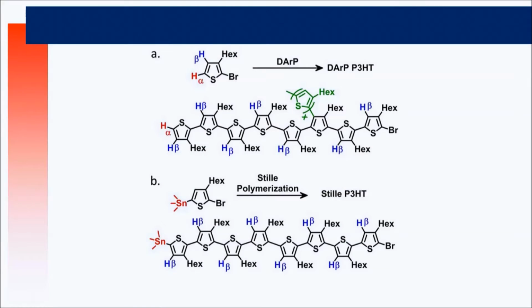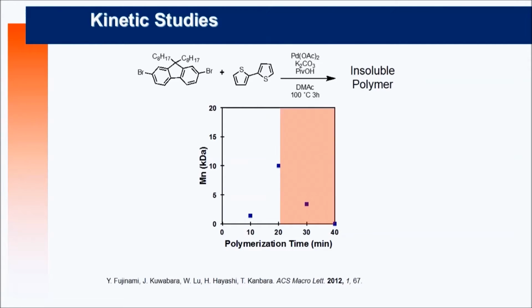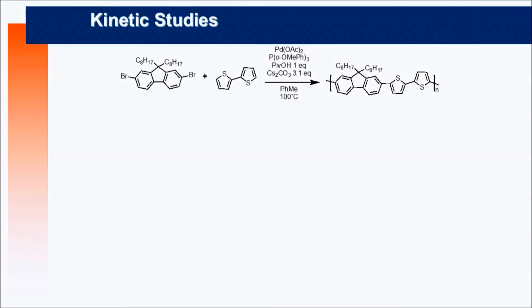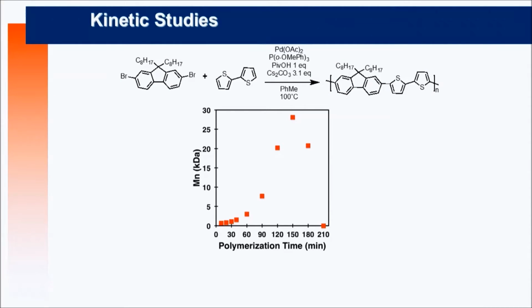I would say it agrees with this idea that cross-linking will occur as a function of time. So what he did, he chose a solvent where the system is less reactive, so we slow down the reaction, and we follow the kinetics. And that's really the typical step growth polymerization mechanism, where you have an increase of the molecular weight as a function of time. So if you follow it carefully, you can go up to 26 number average molecular weight. If you wait too long, you get fully insoluble materials. Is it related to the fact that it is cross-linked, or the molecular weight is too high and processability is decreased? We don't really know. But it's possible, if you stop the reaction here, to get soluble, processable, and useful material.